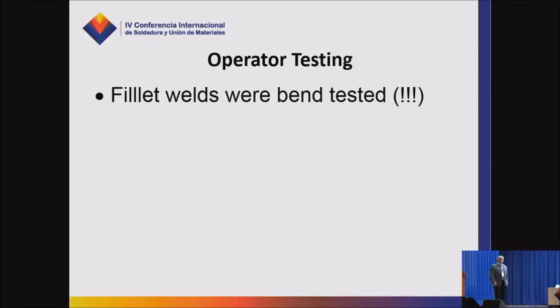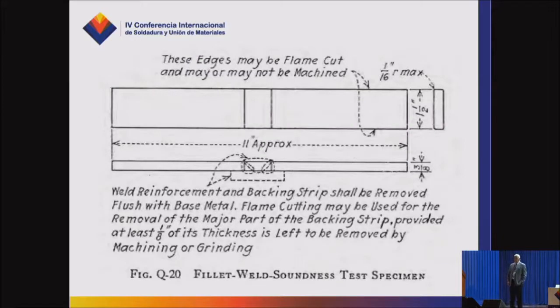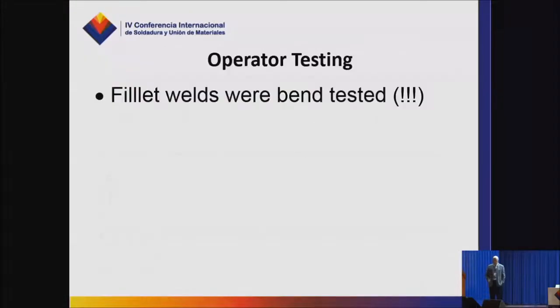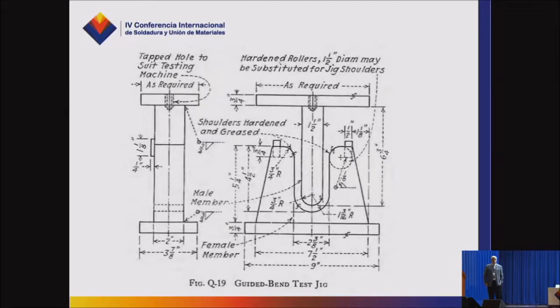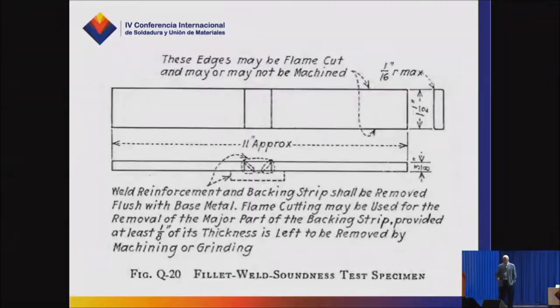Section 9 required that you bend test welder fillet weld tests. How do you do that? Well, the welder welded up a test piece. It'd be a piece of plate. You cut a strip out. But what the welder did was he had a square groove and a gap, and he put 2 fillet welds in on both sides on a backing strip, and then filled it out. And then what you did was you removed the weld reinforcement, you removed the backing strip, and you put that specimen back in this fixture with the root side downward, and if there was any incomplete penetration on the root side, the specimen would fracture. So actually a pretty cool test.